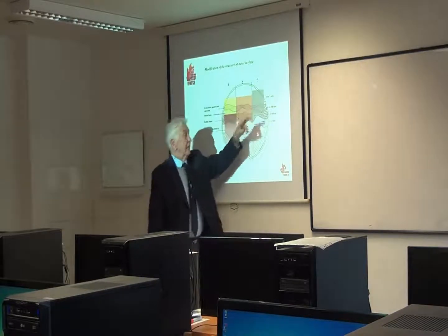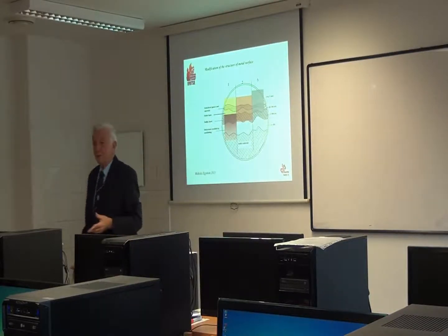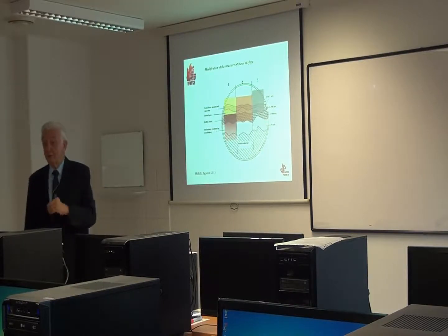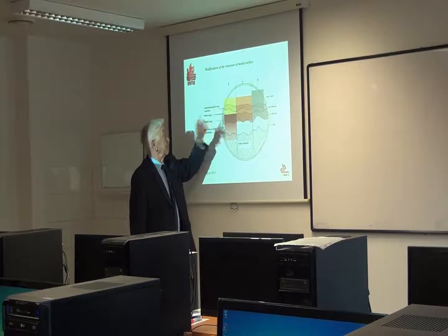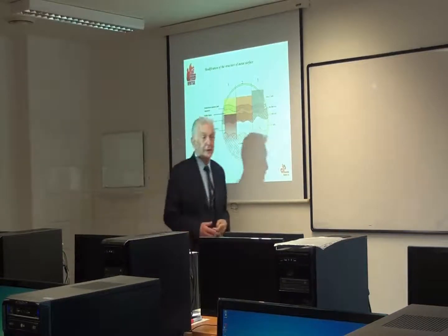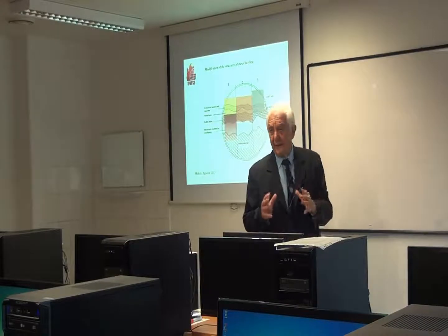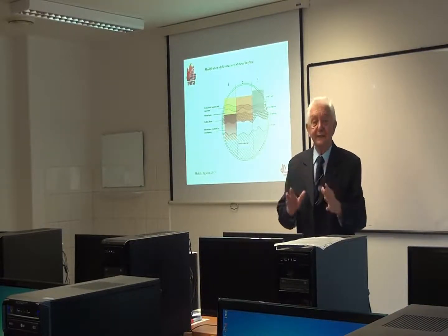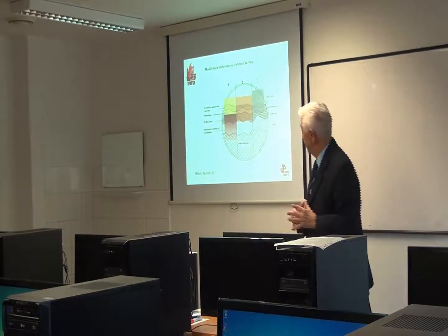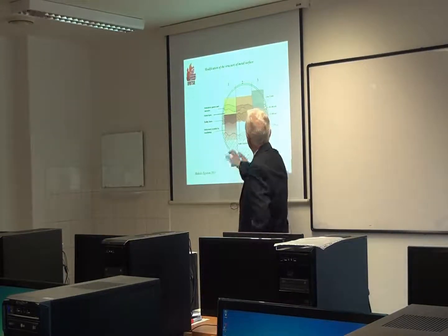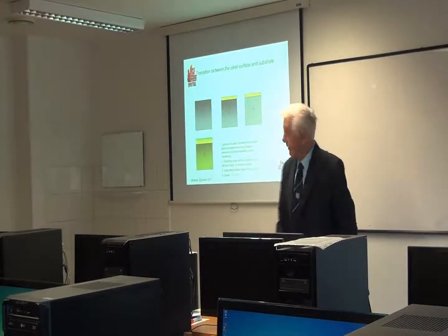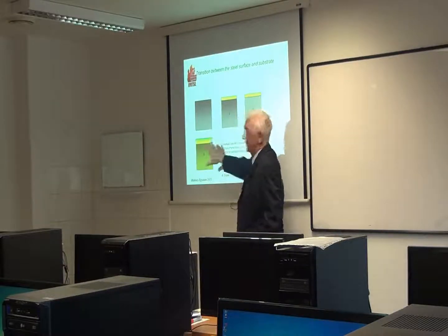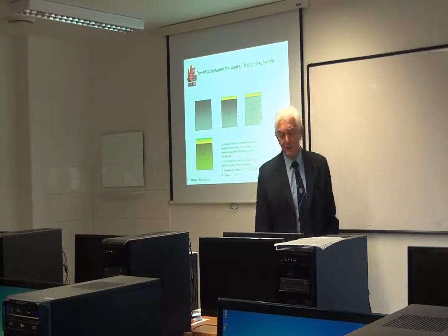Up there is an oxide layer, so all the materials will oxidize. And whatever we do, a small oxide layer will form on the surface. And then, at the outer surface, there are adsorbed gases, or from the lubricant. So there is a special, very thin layer, but it has nothing to do with the structure of the bulk material. So, when we consider all this, just think about the surface engineering that I have shown you. The 1, 2, 3. The 4 is a different matter because it's a little bit special.